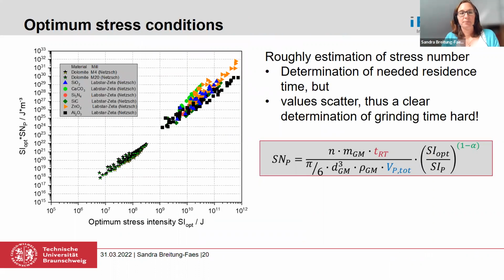And then here I took the optimum stress intensity and took it into relation to the product of the stress intensity, the optimum one, and the product related stress number. And this is the result here. You can see it for the nano grinding experiments, and here below for the different Isomill experiments. When you look from the distance to this curve, you'd say, oh, pretty nice correlation. Yes, it's a good correlation, but when you look a little bit more in detail, you can see, especially for the small mill and the nano applications, the deviation is pretty high.